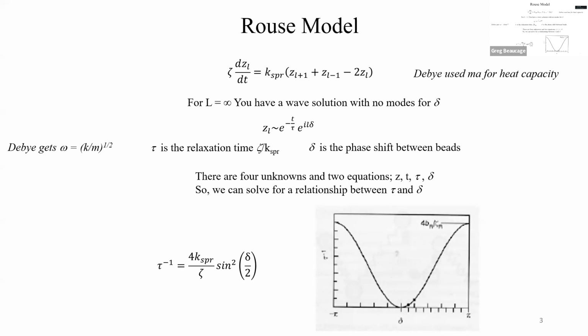I didn't mention that. This is coarse grain. So Rouse actually invented coarse graining in '53, because he has the chain, and he's going to have these units. They aren't Kuhn units. They're units that are larger than a Kuhn unit, large enough that they can follow Gaussian statistics. So the size of his Rouse unit is going to follow R squared and L squared. So you can figure out the size of it to get the friction factor from Stokes' law.